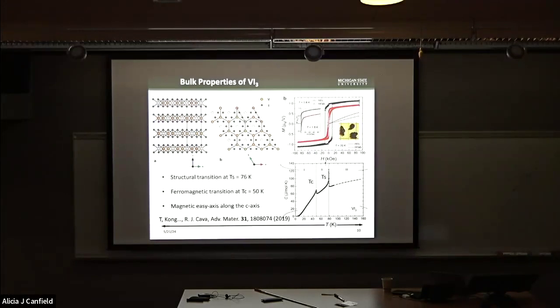So the first compound that I'm going to show you is vanadium triiodide, which has a similar crystal structure to chromium triiodide. Here the magnetic ions, the vanadium ions, again occupy the honeycomb lattice. And from the bulk heat capacity and magnetic susceptibility, we know that the system has a structural phase transition occurring at about 76 Kelvin, followed by a ferromagnetic phase transition at about 50 Kelvin. And from the magnetic susceptibility measurements, it was argued that the easy axis was along the C direction.